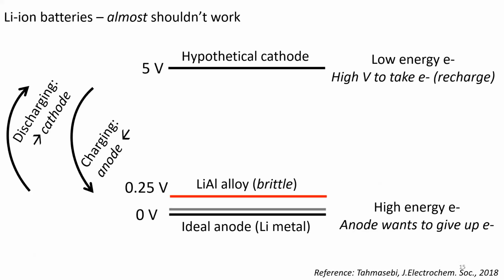The other problem with this is that the electrons in lithium atoms that are trying to make an alloy with aluminum are a little bit lower in energy than they are on our graphite anode. So when you go to recharge a battery and you have an aluminum current collector, the lithium ions preferentially go to the aluminum and make that alloy. So that happens before the lithium ions go back into the graphite. So we can't use aluminum as the anode current collector.